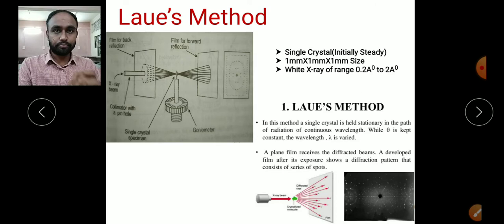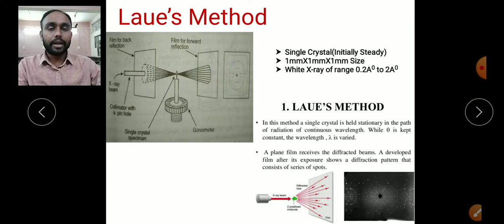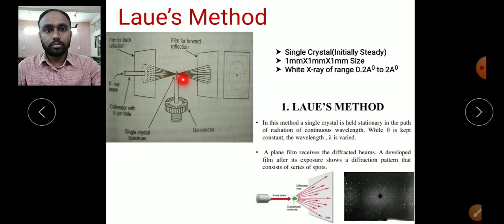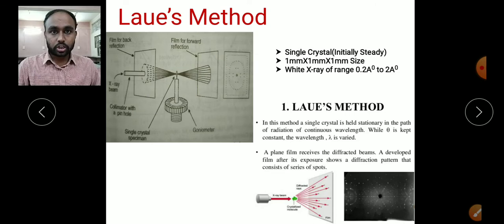The light is diffracted and scattered rays come toward the film. Not a single ray but a bunch of rays are incident on the crystal. Considering any two rays diffracted from an atomic plane — if they meet on the film in phase, they interfere constructively and we get a bright point on the film.